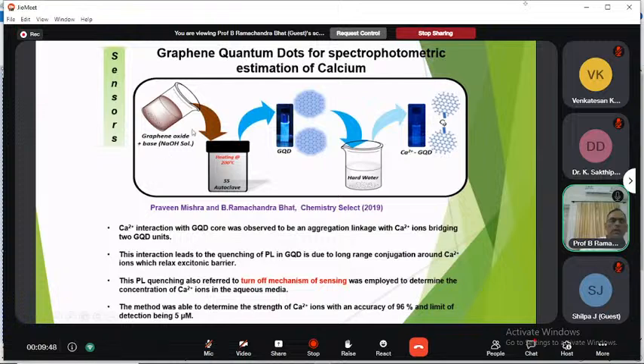where you can see that the graphene oxide is taken and autoclaved, and then you get a GQD. This GQD shows photoluminescence, PL, and when you put it into water, it loses its photoluminescence. So you can see here there is no photoluminescence, no glow here. And why is it so?